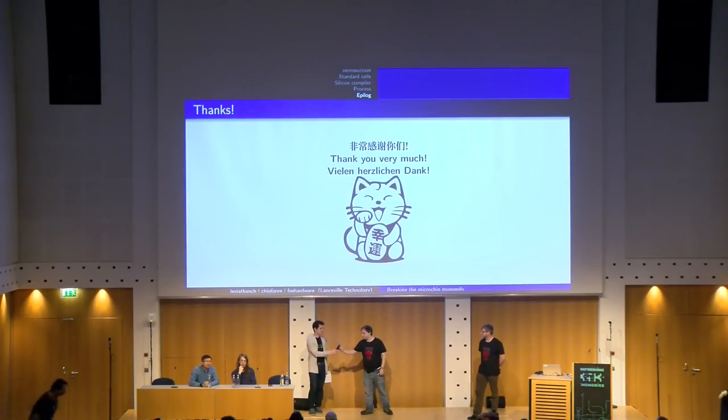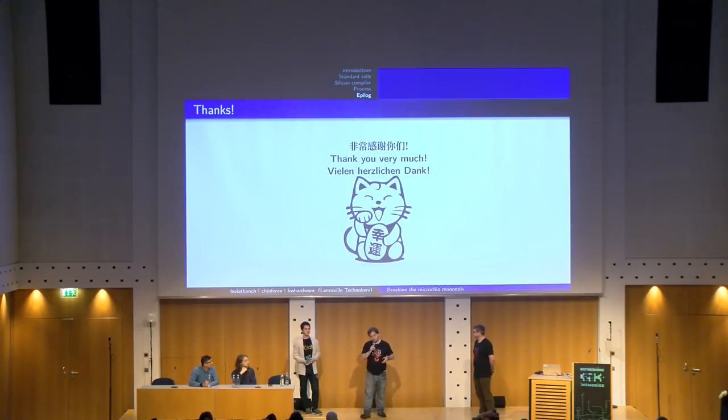Microphone two. Hi. Why did you go for the twin well process as opposed to the simpler single well? That's a good point. That's also something to do with portability. If you have a different vendor or different supplier for the substrate, it might be an N-doped or an undoped substrate. With the twin well architecture, in the N well we also built P wells, so we actually have stacked wells in the N well and P wells, so it's actually a one, two, three, pentagon well. I don't know. And that's just so that you can shift the doping of the N and the P substrate so that you fit LibreSilicon requirements and still have the physical properties ensured by LibreSilicon, no matter whether you get your substrate from Great Britain or from Taobao.